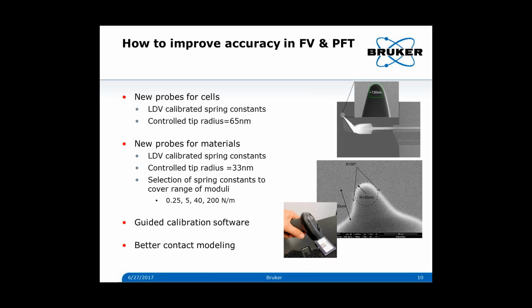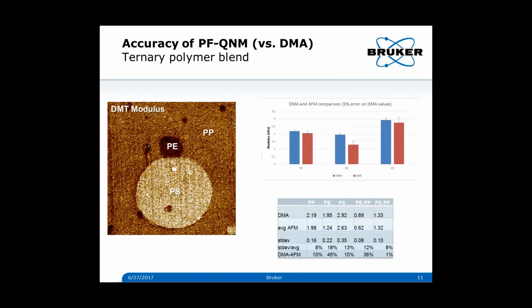And we implemented the spring constant since they're calibrated at the factory with the laser Doppler vibrometer. They can be scanned in by barcode, and you just choose which probe out of the box you're using, and you get accurate measurement of tip radius and spring constant. Here's the kind of result you can expect.